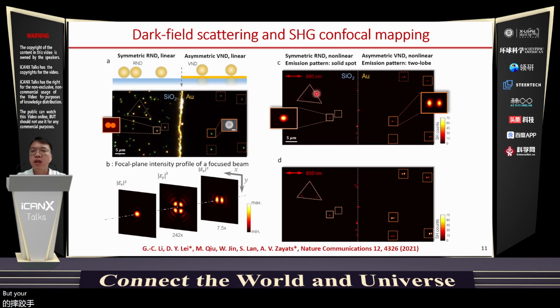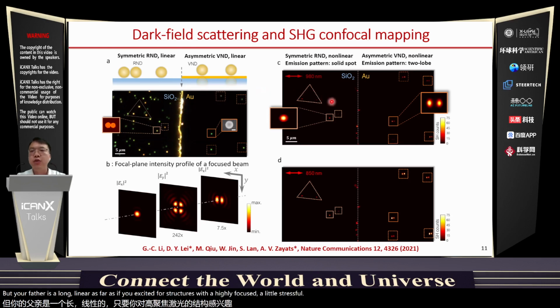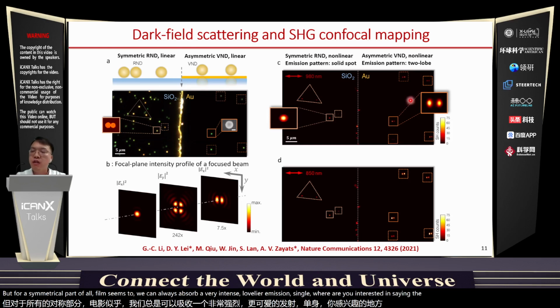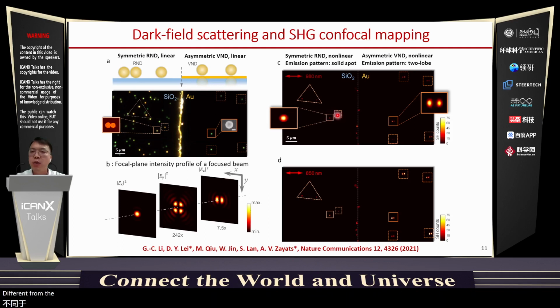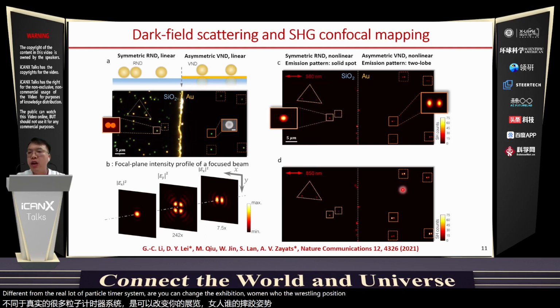But you find that in the nonlinear response, if you excite these 2 structures with a highly focused femtosecond laser beam, you will find that only a few real nanoparticle dimers can be lit up under the femtosecond laser illumination. But for the asymmetrical particle on film system, we can always observe very intense nonlinear emission signal. A very interesting phenomenon here is that for each nonlinear emission pattern, we observe a 2-lobe shaped emission pattern that's quite different from the real nanoparticle dimer system. And if you change the excitation wavelength to the resonant condition, you can even get a stronger nonlinear emission pattern. So what's the reason for that?